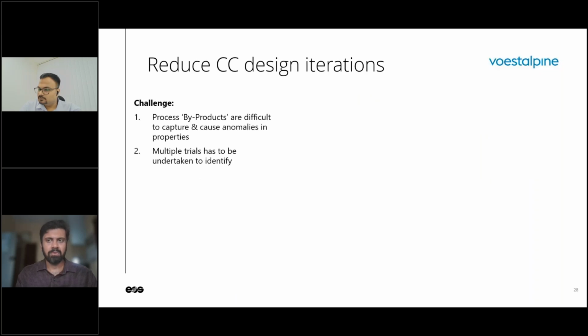Another thing also comes from voestalpine is when they did for the 789, the Corax material, right? So there are some process defects come in. Now, typically when we talk in terms of castings even, there are process defects such as blowholes, such as hot tear, things like that, right? So similar to that, in additive manufacturing also, we have such process defects that come in, for which, depending on geometry, they tend to do multiple prints, cut it, check it in lab, and see whether some process parameters has to be optimized or not, right?